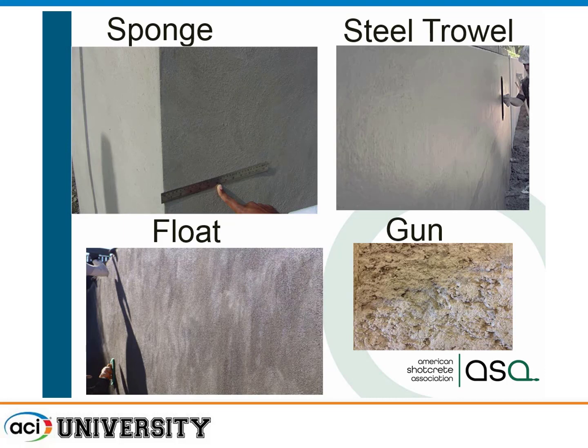In repair applications, though, if it's a highway pier, we can match whatever the texture was before. Now, one of the things we can't match is color, because 50 years ago, concrete wasn't made of the same materials that we're using now. And we're using fly ash, silica fume, slag. Those actually affect the color. So we can match the texture, but not the color. So if an owner is looking for a consistent color, maybe use a cementitious coating that allows you to still have that concrete color, but provide it consistently.